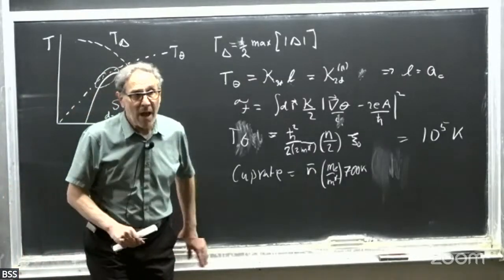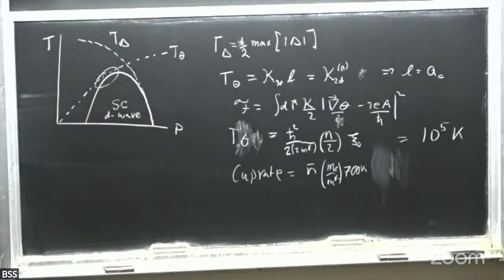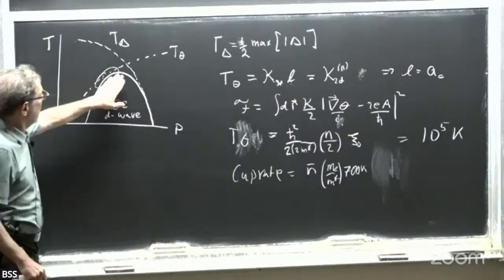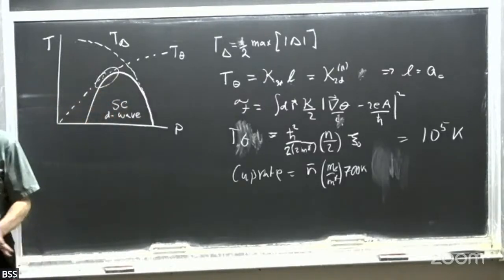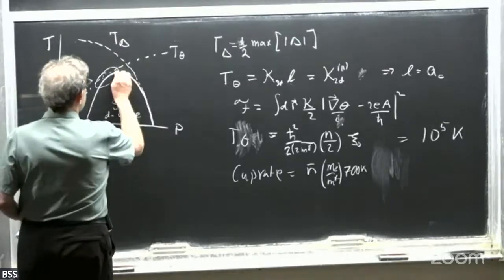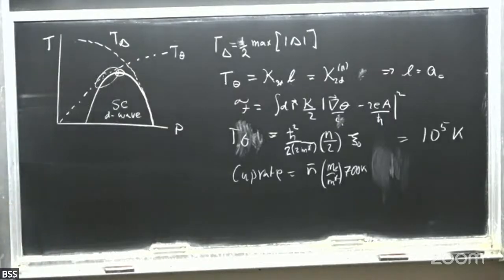So there are a lot of things about this sketch that were right. I think there's now no doubt that phase fluctuations are important for the cuprates. For instance, there's data on very clean, optimally doped materials that show very cleanly, within 10% of Tc, that you see 3D XY behavior. This has been seen by Bonn and Hardy in the temperature dependence of the superfluid density below Tc, and it's been seen by Meingast in really brilliant experiments on the thermal expansivity, which is expected to have the same critical behavior as the